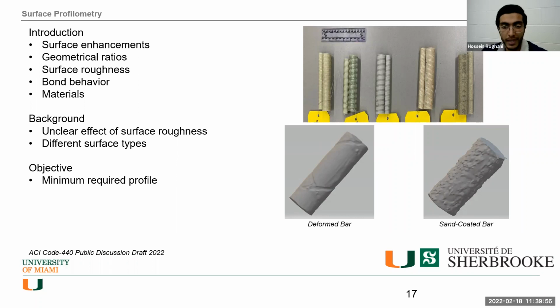I mean, surface enhancement, which is the first, let's define the surface enhancement. The surface enhancement is the treatment applied or created during the manufacture of the FRP reinforcing bars, or also in steel bars. We have almost the same thing, in several forms. I mean, you can do the sand coating, you have the spiral winding, you have the machine grooves, or other methods, or a combination. For example, we have some rebars that are sand coated and also they are helically wrapped. So they have deformation and also they have the sand coating.